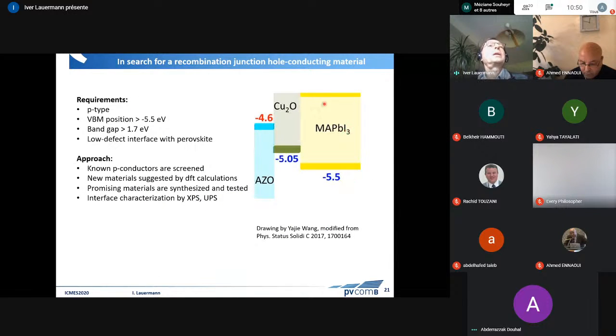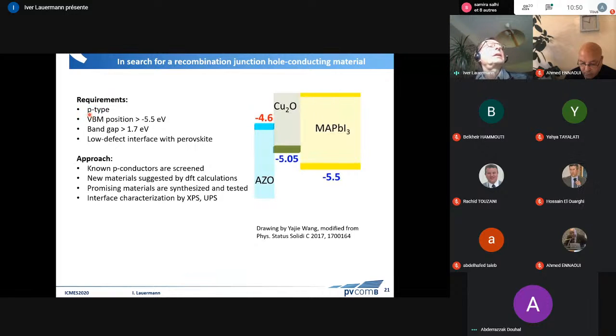And now I zoomed into this recombination junction. This material in this specific configuration that we use has to be a p-type material with a certain position of the valence band. It should have a large band gap because the long wavelength light has to pass through. And what we do is we screen known p-conductors. We also have partners that use DFT calculations to provide new materials, the University of Paderborn.